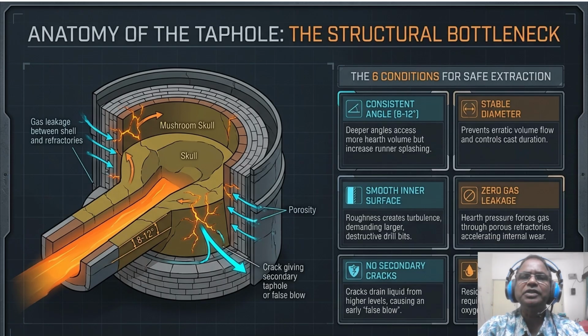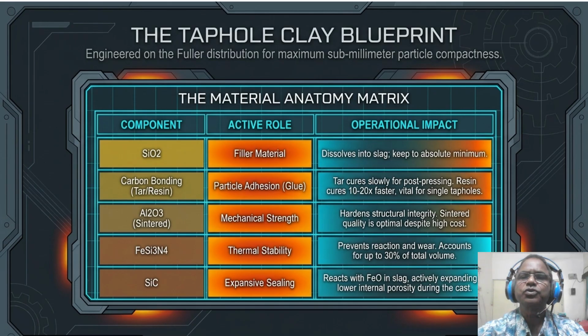So look at the material anatomy matrix. We are not just using a mud, we are using a composite of SiO2, carbon, alumina, silicon nitride. Notice the operational impact of the carbon bonding. Tar bonded clay cures slowly, but resin bonded clay cures 10 to 20 times faster. For single taphole operation, resin is non-negotiable. There is no doubt about it.